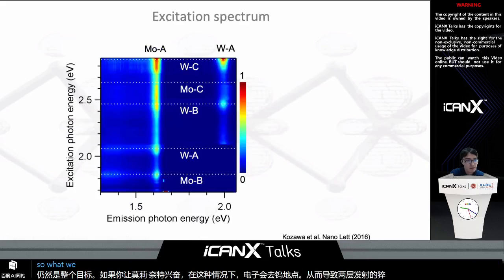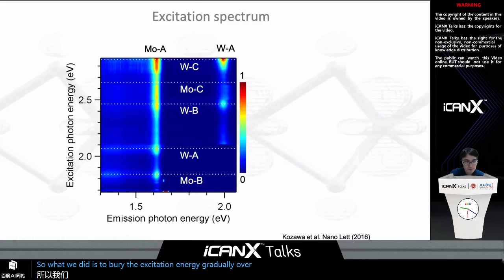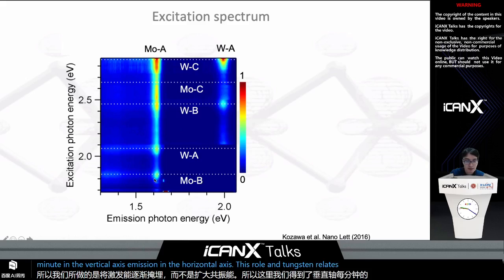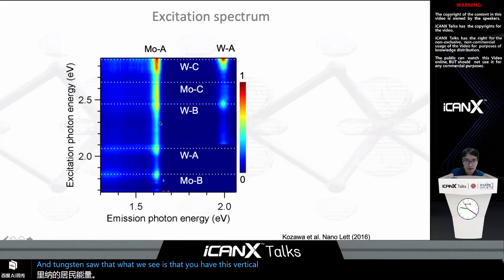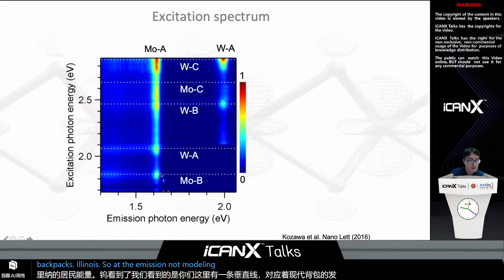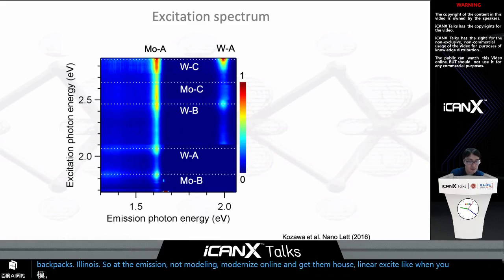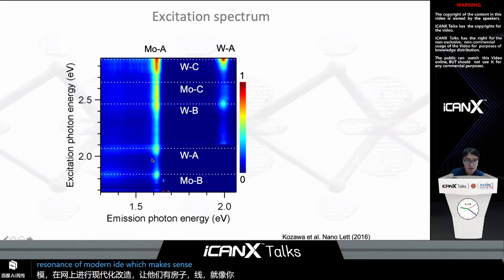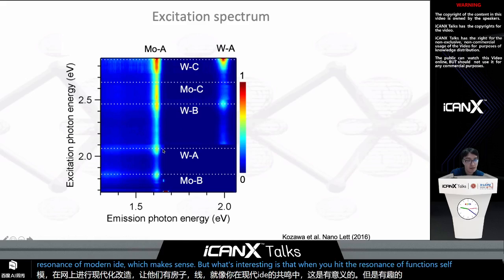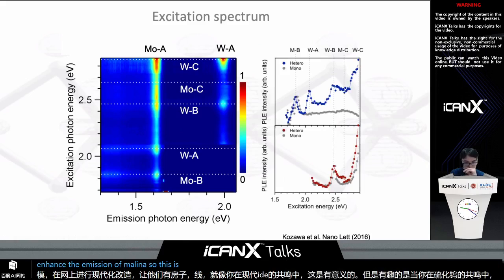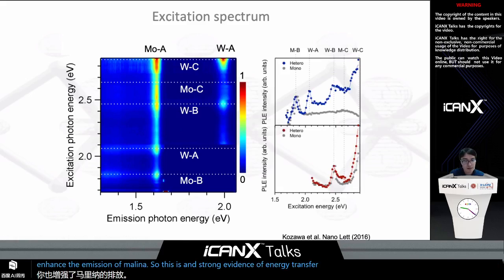So what we did is to vary the excitation energy gradually over the exciton resonance energies. Here we have the excitation photon energy on the vertical axis and emission on the horizontal axis. Mo and W represent the resonance energies of molybdenum selenide and tungsten sulfide. What we see is this vertical line here, which corresponds to the emission energy of molybdenum diselenide. The emission of molybdenum selenide gets enhanced when you hit its resonance, which makes sense. But what's interesting is that when you hit the resonance of tungsten sulfide, you also enhance the emission of molybdenum selenide. So this is strong evidence of energy transfer from tungsten sulfide to molybdenum selenide.